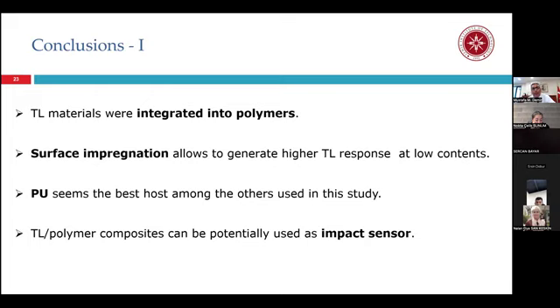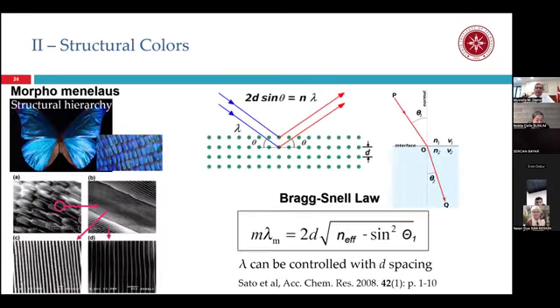For the conclusion of the first part of the talk, I showed you the integration of triboluminescent material with polymers via two ways, and surface impregnation is one of them and allows generating a high triboluminescence response. Polyurethane seems the best among the other two transparent polymers, and they can potentially be used as impact sensor material. As you remember, increasing the height of the ball increases the intensity of the triboluminescence signal. For the second part of the talk, I'm going to present structural coloration.